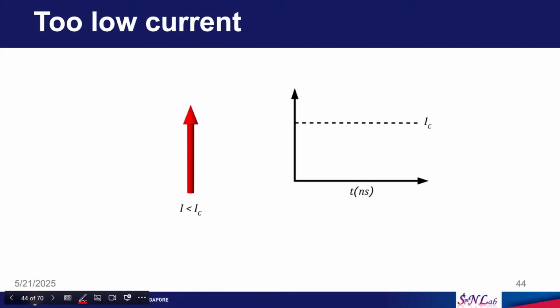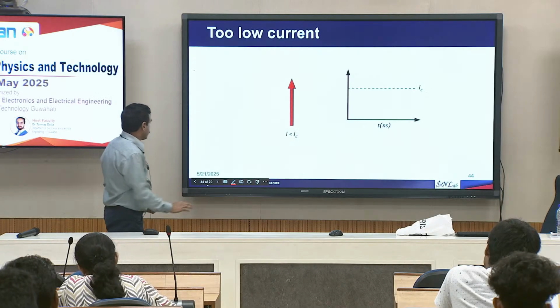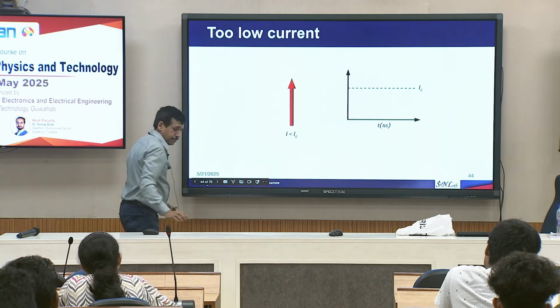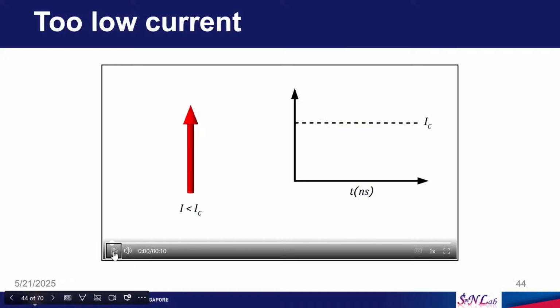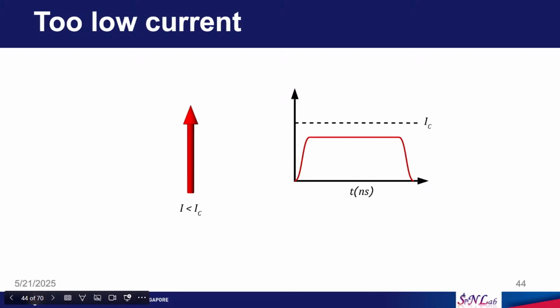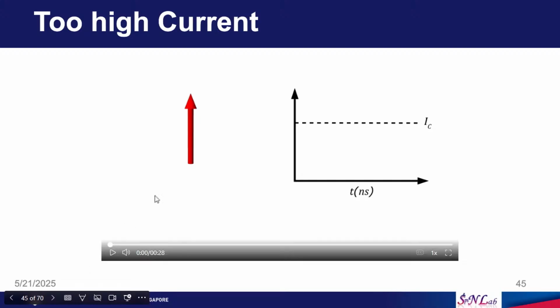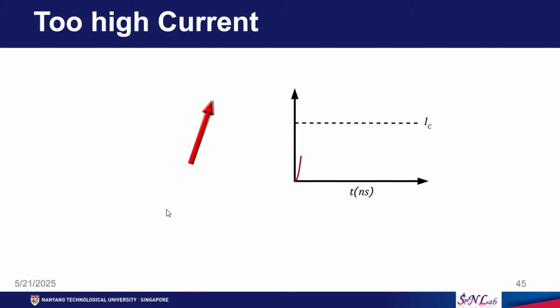Okay, so, I will show a few animations. Here the pulse you apply, the current is below the critical current. So, you see that the magnetization just oscillated, then it did not switch. If the current is too high, if it is more than the critical current, then it can switch faster. Okay. So, even though your pulse width is so large, you can switch much before your pulse ends.